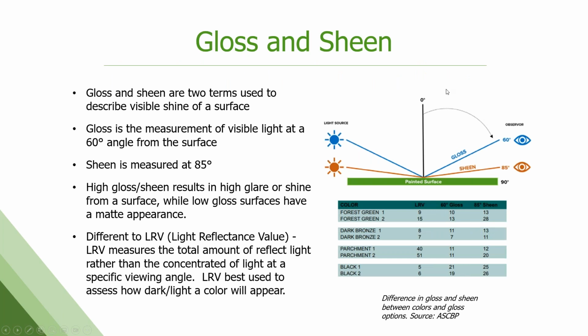Gloss and sheen, again, two terms that sometimes get confused with light reflectance and solar reflectance and other properties we talk about. This is the visible shine off of a surface measured at a specific angle. Gloss is the measurement at 60 degrees. Sheen is the measurement at 85 degrees. High gloss and sheen is going to be high glare, high shine off of a surface. Low gloss, low sheen surfaces will have a very matte or flat appearance.